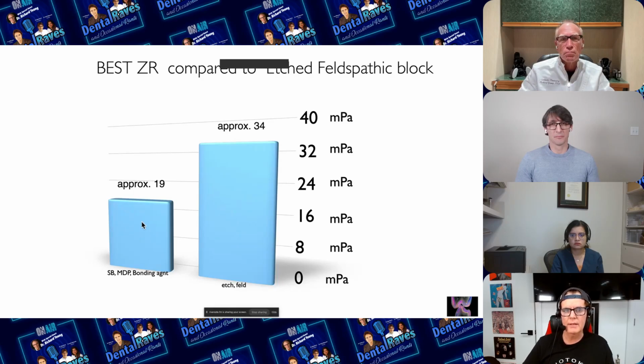All right, so I think it was 8 or 10, I can't remember off the top of my head, but it doesn't matter, because we got enough specimens and we saw the behavior, okay? This was going to turn into a full paper, and the reason why I can't give you all the exact numbers is because Anvita is going to be doing the full paper on all this data with really, really good statistics, but with your eyes, you can see some of these things. So the interesting thing is we were up around 35 megapascals on the etched Empress. Very similar on Emax, okay? So they almost behave the same, but fascinating.